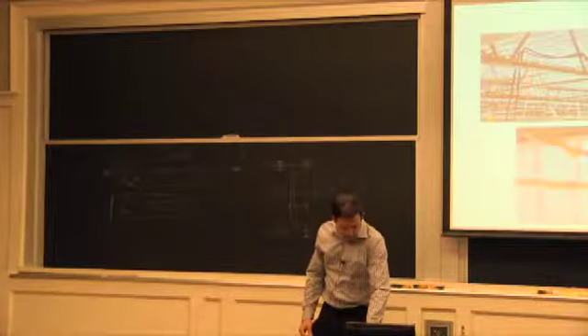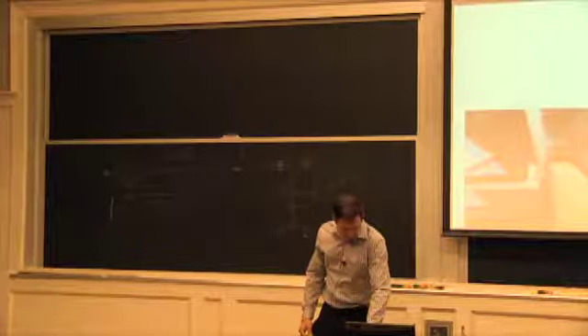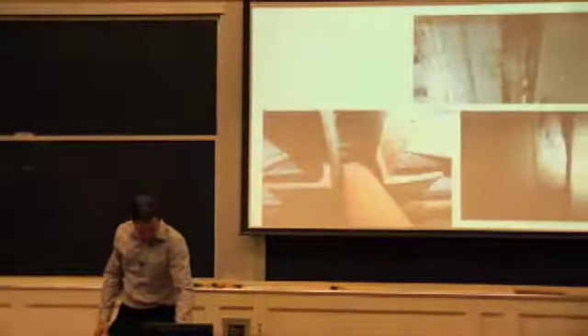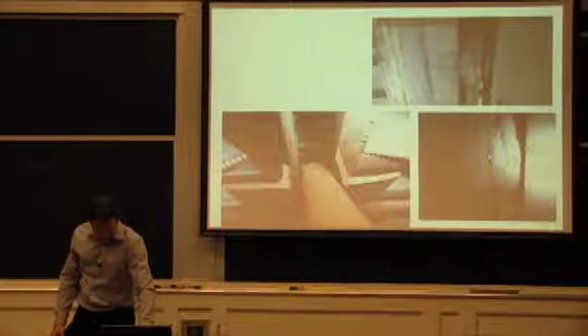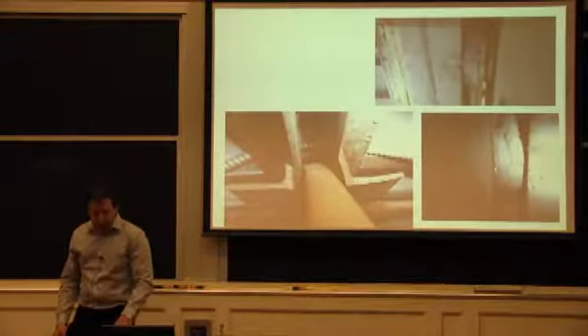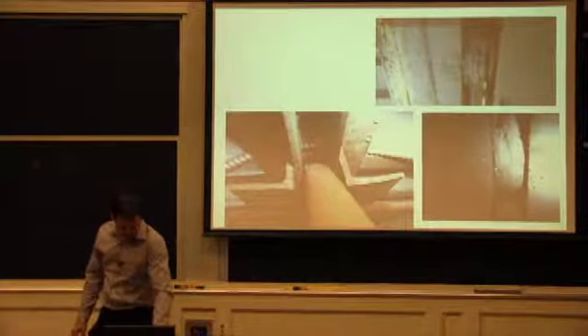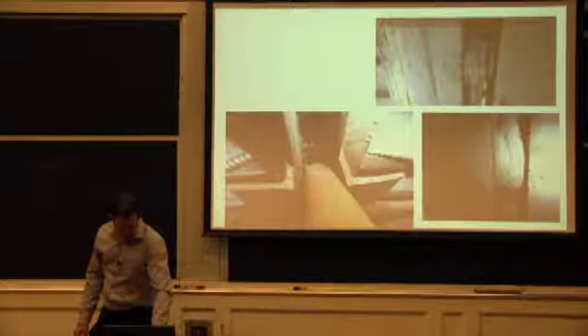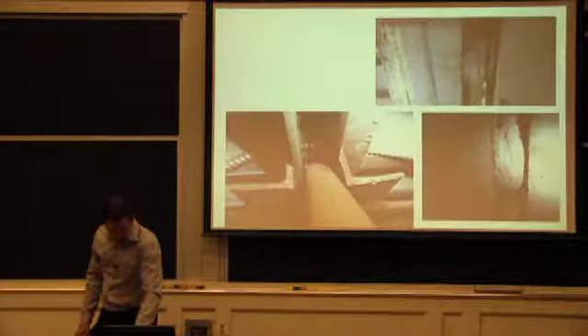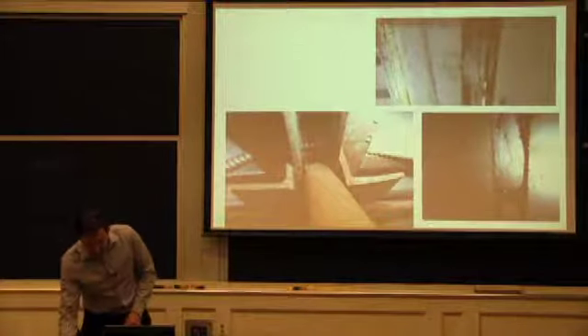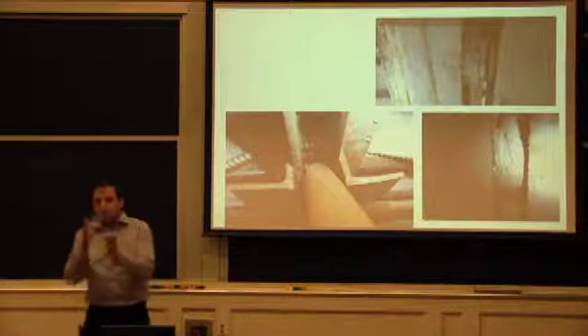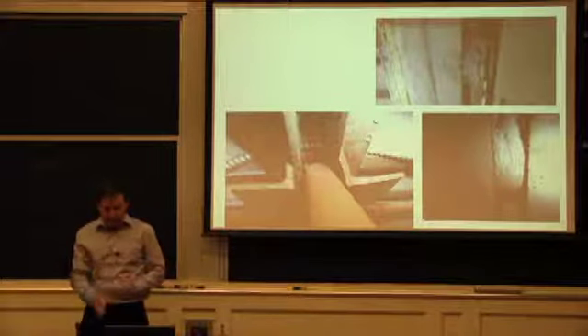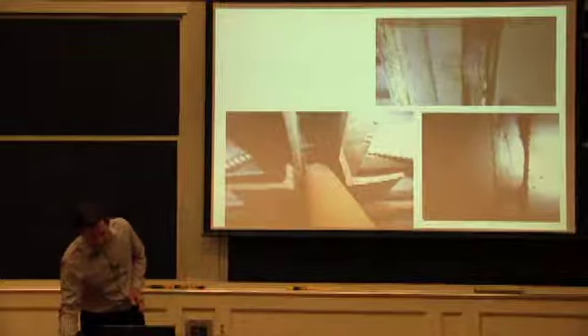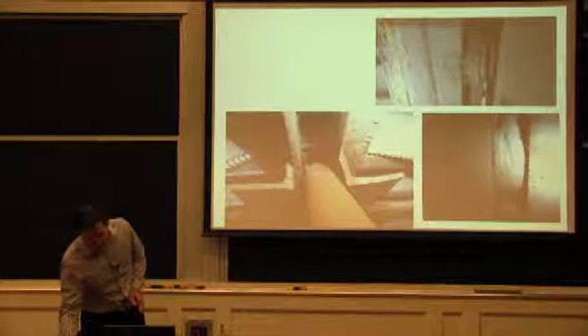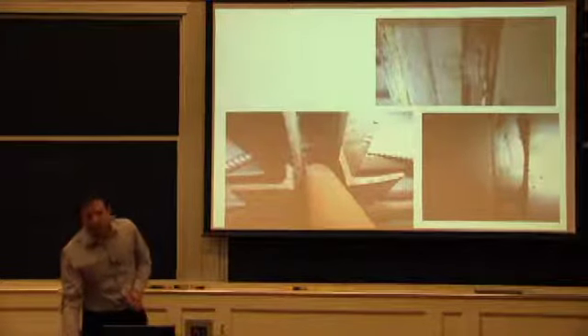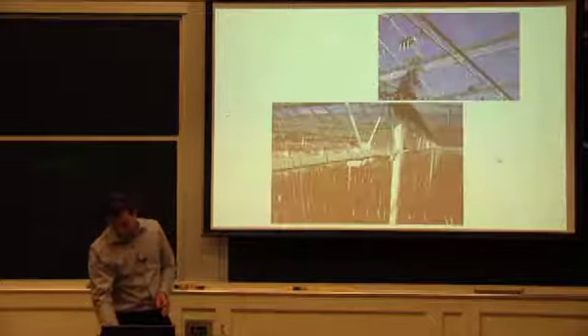So talking about weld fusion, maybe the last thing. These are some of the weld failures. So you see here that it's just breaking off. We're looking at this location, but from underneath here. And the issue becomes, it shouldn't fail just like that, right at the interface between the angle of the joist and the welded bead. You're looking at the welded bead here, and it's just splitting apart. And it was very common.